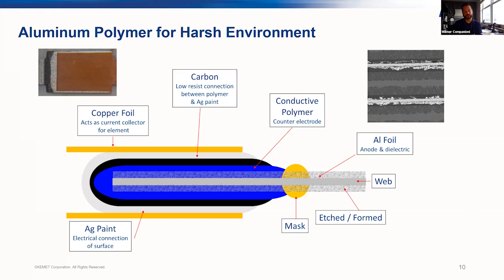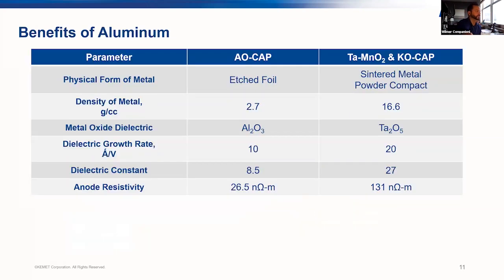Now, what's different between this launch and recent launches of aluminum polymer is that this is actually capable of harsh environments. So we can go up to higher temperatures and harsher conditions that require more reliability than past launches, up to 125. So some of the comparisons between aluminum and tantalum are listed on the screen. Now the dielectric constant of aluminum oxide is lower than that of tantalum. So, by the very nature of it, you do get less capacitance.